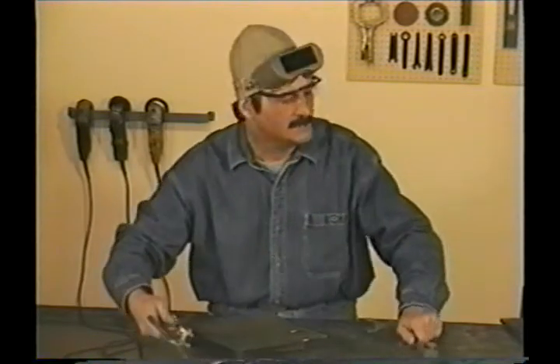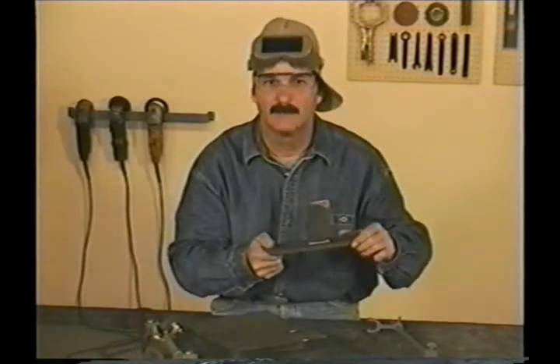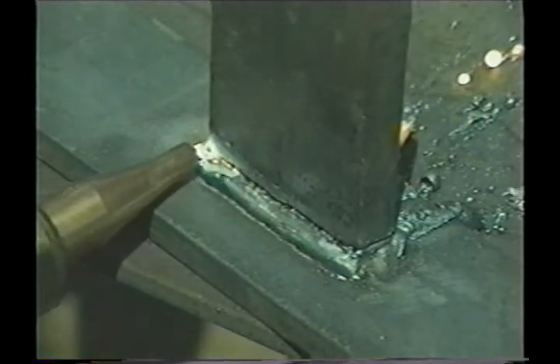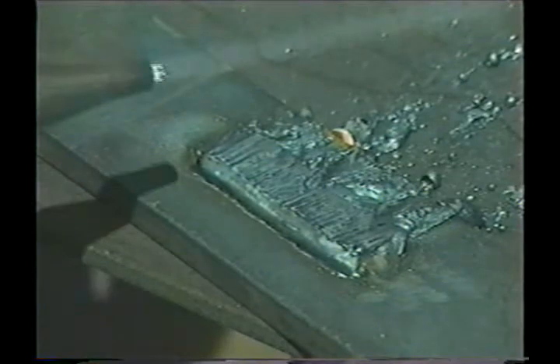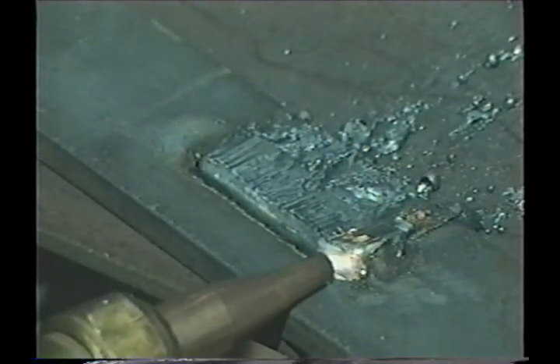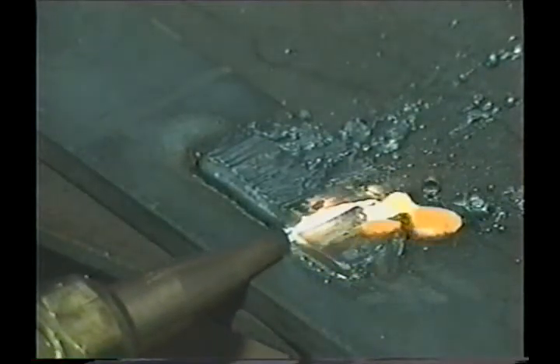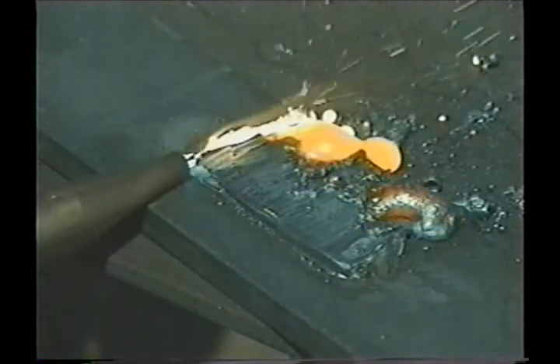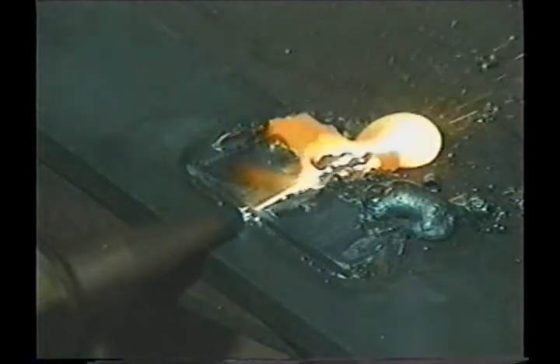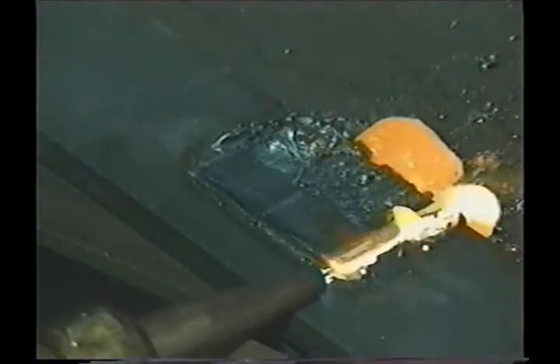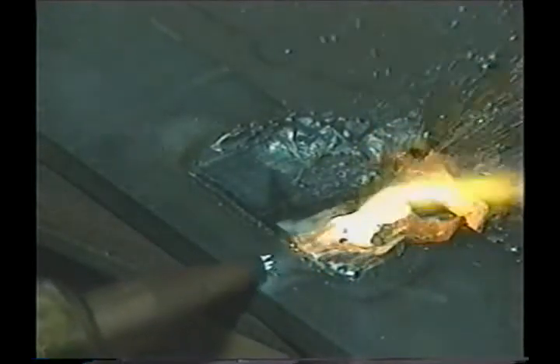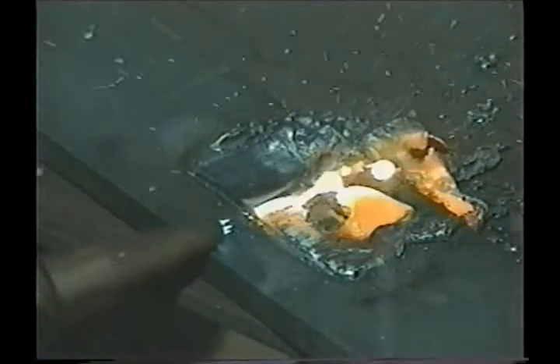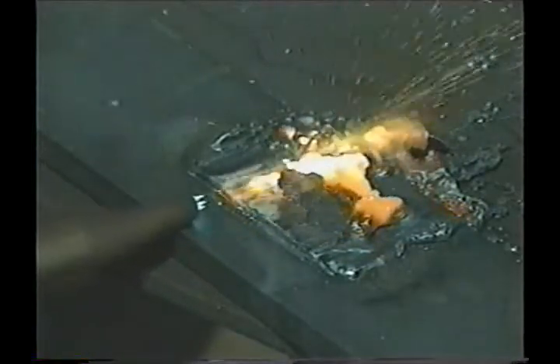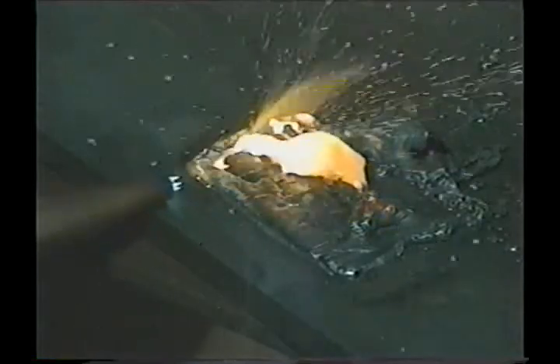In making repairs, you may also run into the situation where you have to cut apart a T-joint. You can cut just above the weld, then start slicing it off. When you get close to the base, you start washing off the metal. Back the torch away and ease off the cutting jet lever to slow down the cutting jet. Watch the back side of the cut stream to make sure it's not gouging into the base metal. You can get pretty close washing that metal off, and it saves on the grinding time.